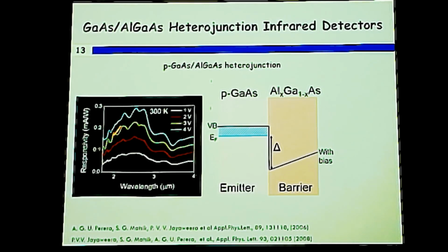So the performance actually depends, usually less than 1 volt or more than 1 volt. If the device has very high resistance and a very thick layer, then the bias needs to go high, even in the 5-10 volt range. But it really depends, and it's actually the field, meaning the bias divided by the total thickness of the barrier. That is important, and the field for these devices operating in the mid-infrared is usually in the range of 100 kilovolts per centimeter or something like that. I'll show you the bias range for operation in actual devices later as well.